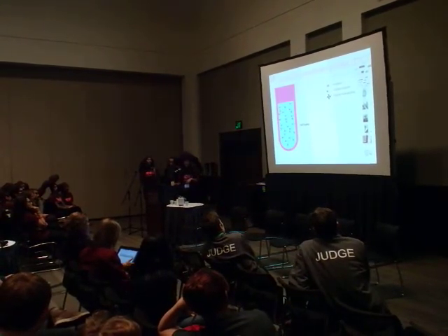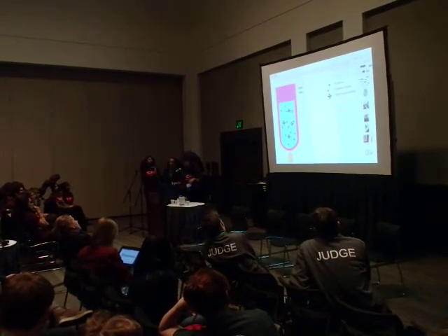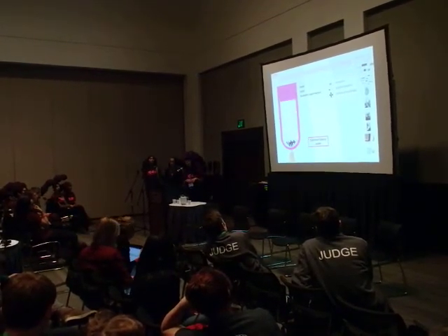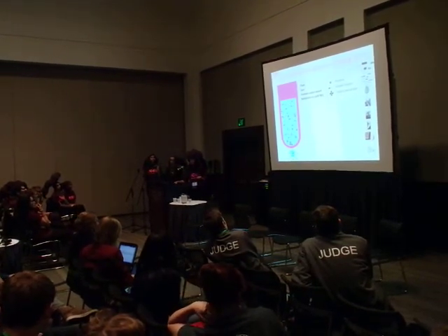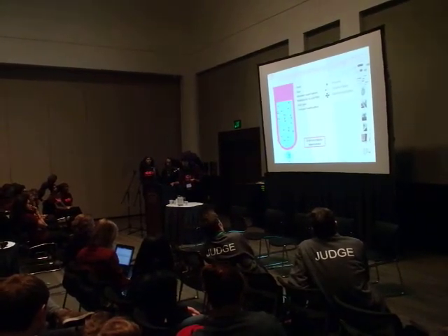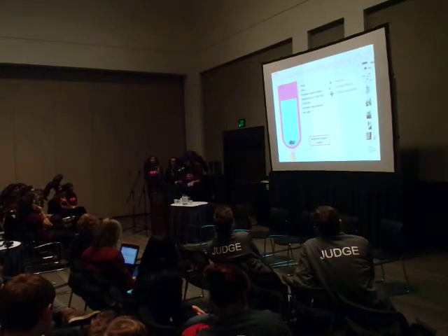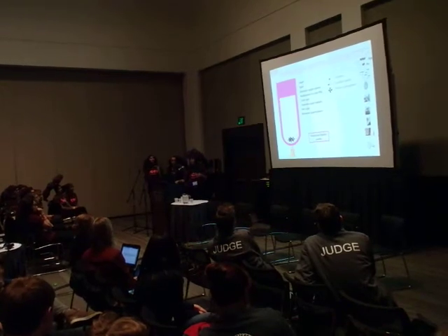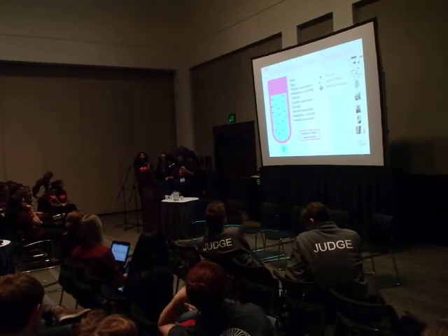So we began with our cell lysate. After warming, the elastin will aggregate, and the hot spin permits the precipitation of the elastin in the pellet. After that, we remove the supernatant and redissolve in cold PBS. So the cold spin permits the precipitation in the pellet. After transferring the supernatant, the hot spin will precipitate all the protein in the pellet, and our pellet will be enriched in elastin. After removing the supernatant, we dissolve in cold PBS, and we obtain elastin